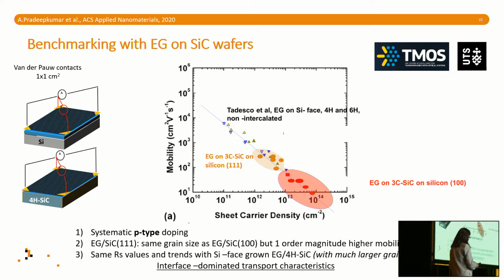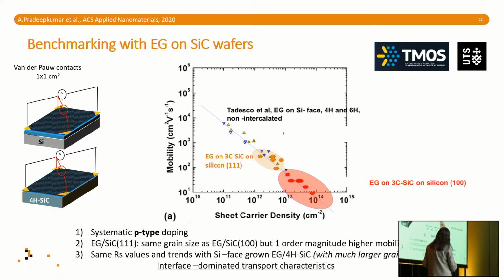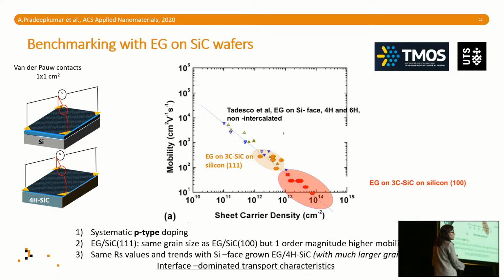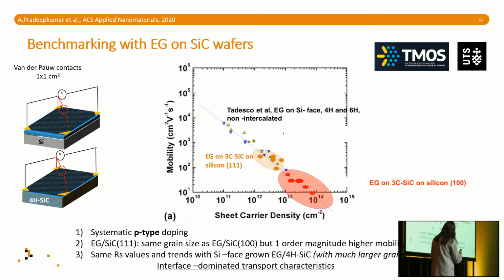Now, for those of you who are not familiar, supported graphene has a typical power relation between mobility and sheet carrier density. Of course they are connected, they don't change independently. And so they would appear on a log scale like a straight line. And all of those points that correspond to a straight line correspond to roughly the same sheet resistance. Now, of course, you have higher mobility for lower sheet carrier density and vice versa. So the higher the carrier density, the lower the mobility. Now the interesting part here is that we have superimposed some of our numbers. We were using quite big samples, so 1 by 1.